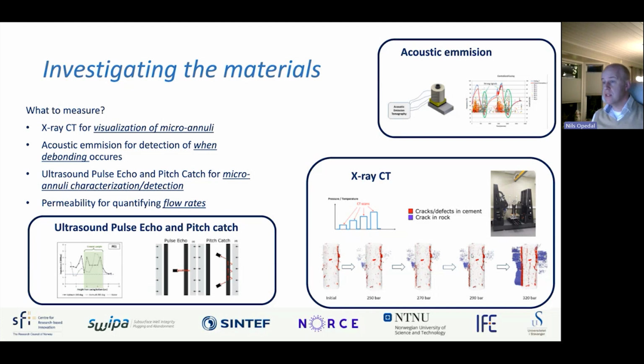The acoustic emission is helpful for detecting exactly when a debonding occurs, because we essentially just listen to a sample. So we place different sensors on the outside, apply, for instance, a heating cooling protocol as indicated by the figure, so ramping up or ramping down, and essentially just listening to when we have a higher density of small fractures and movement of the specimen. This is a nice feature to be able to exactly pinpoint when things are happening in relation to changes in temperature, but it doesn't really say that much exactly what it looks like and where it is. So that is where the CT comes in handy.